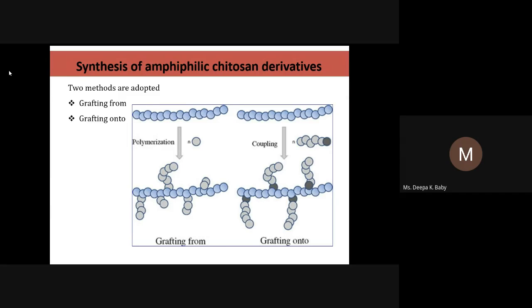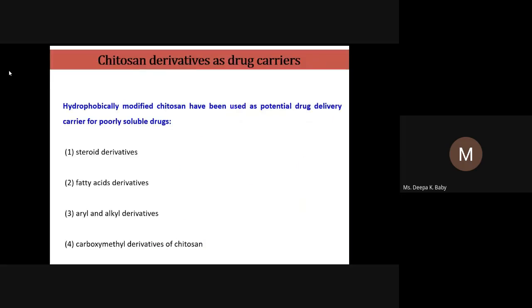In the grafting from method, first chitosan is taken as a backbone, and to it you are adding small molecules, thereby another polymer is made on the backbone. That is grafting from. Second process is grafting onto. Grafting onto means you have the same chitosan backbone, you are taking another polymer and using a functional group, you are attaching this polymer to the backbone. That is grafting onto. Generally, chitosan can be modified with these derivatives. Steroid derivatives can be used, fatty acid, aryl and alkyl, and carboxymethyl derivatives of chitosan can be used.